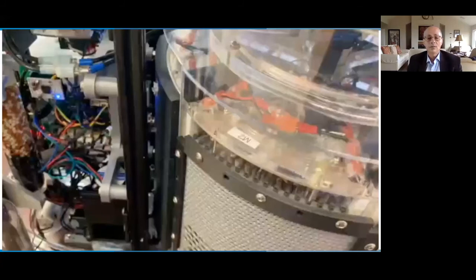The amazing thing here in this device is that we're only using 100 grams of MOF, only 100 grams of MOF. We're doing around 200 cycles, and we are harvesting around 5 liters per day. So 100 grams of MOF, 5 liters per day. That's basically a tabletop device. Not this particular one, but the next generation will be a nice tabletop device that delivers around 5 liters per day based on 100 grams of MOF.